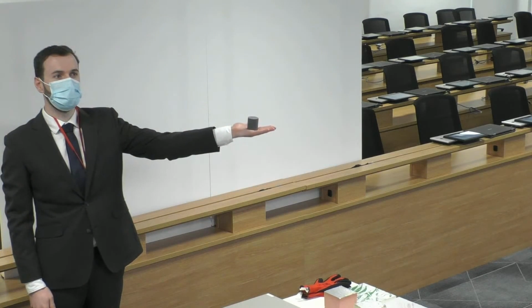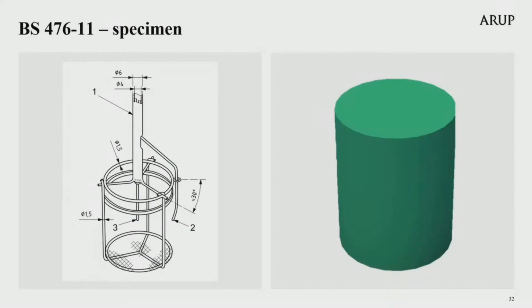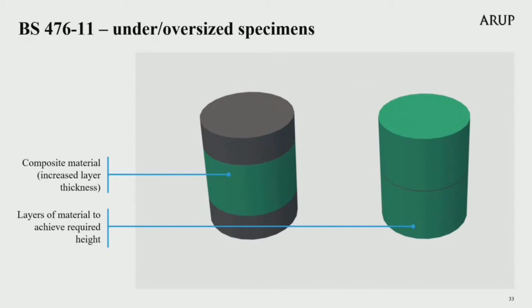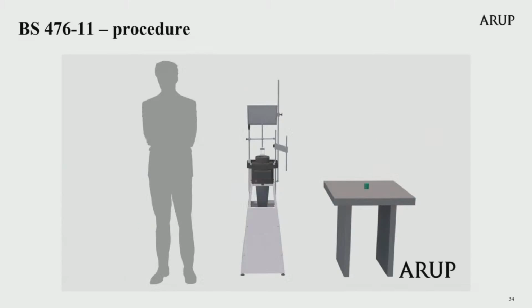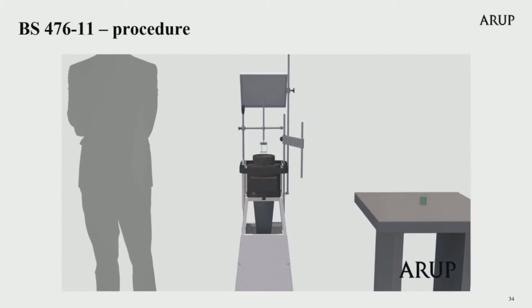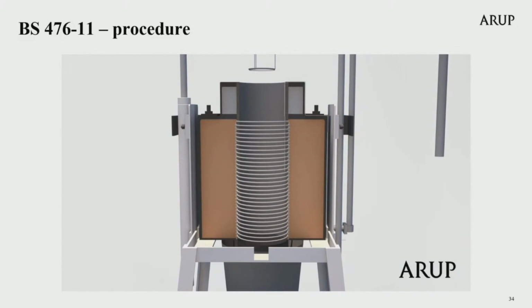The specimen is then put into the holder, as shown in the image on the left, and again a thermocouple is inserted through a 2 millimetre drilled hole at the top of the specimen. Again, specimens must meet the minimum height required for the test specimen of 50 millimetres. For a material with a normal thickness greater than 50 millimetres, it should be reduced. If the thickness of the material is less than 50 millimetres, the right height should be made using a sufficient number of layers of the material or adjusting the material thickness. The video on screen now shows this test procedure.